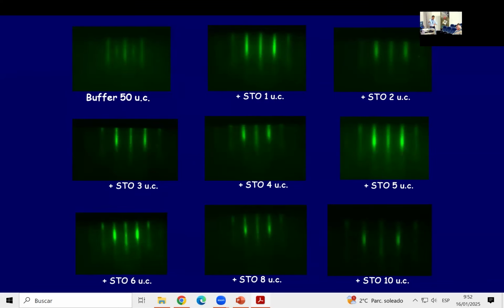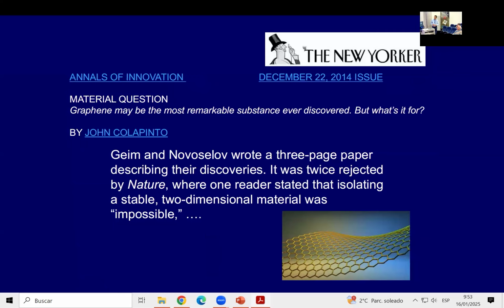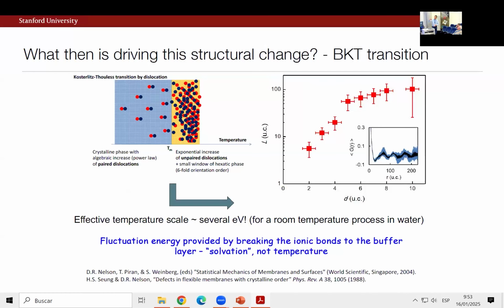Let's say here we have one layer of strontium titanate living on our buffer layer. It's heterogeneous, but this is a 3D system, right? That's acting as a substrate for this topmost layer. So this thing is crystalline. There's nothing to worry about stability, et cetera, right? And then whatever is happening, we haven't seen or done a dynamics experiment, is happening between starting with this crystalline fine structure and examining what happens if we lift this up and simply take this directly onto a TEM grid.